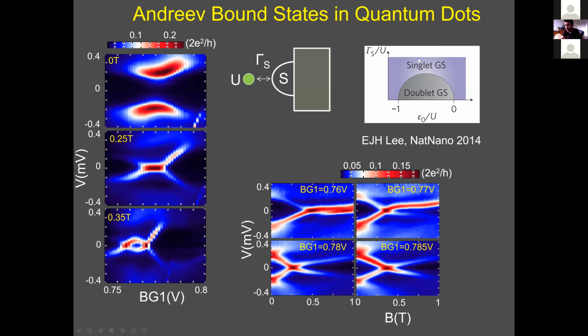Well, there is another possibility for what can happen. If we apply a magnetic field, then the singlet and doublet states Zeeman split, and the energy difference between singlet and doublet starts to go down. So we can have a quantum phase transition as a function of field. And this is what happens here. At this field, the singlet and doublet energy is 0, and we have a 0 bias peak just at this field. Because if we keep going, it splits into loops and it evolves.